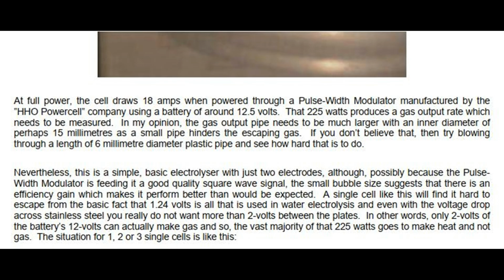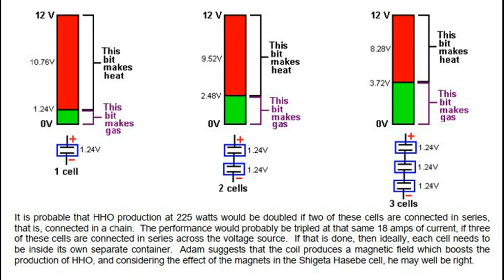Nevertheless, this is a simple, basic electrolyzer with just 2 electrodes, although, possibly because the pulse width modulator is feeding it a good quality square wave signal, the small bubble size suggests that there is an efficiency gain which makes it perform better than would be expected. A single cell like this will find it hard to escape from the basic fact that 1.24 volts is all that is used in water electrolysis, and even with the voltage drop across stainless steel, you really do not want more than 2 volts between the plates. In other words, only 2 volts of the battery's 12 volts can actually make gas, and so, the vast majority of that 225 watts goes to make heat and not gas. The situation for 1, 2 or 3 single cells is like this.